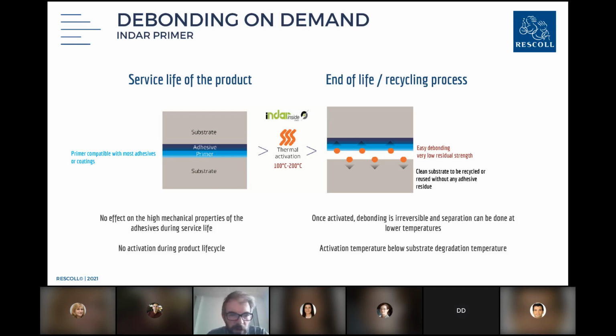Here is another view of what I was just explaining. For bonding, you have the substrate bonded with the adhesive, and the primer located on the substrate you want to debond. In the case of coating, it can be substrate, primer, and coating instead of adhesive and substrate. And then you have the thermal activation, and the mechanical triggering after heating, which induces weakening of the primer layer and easy disassembly of the coatings on top or the substrates bonded on top.